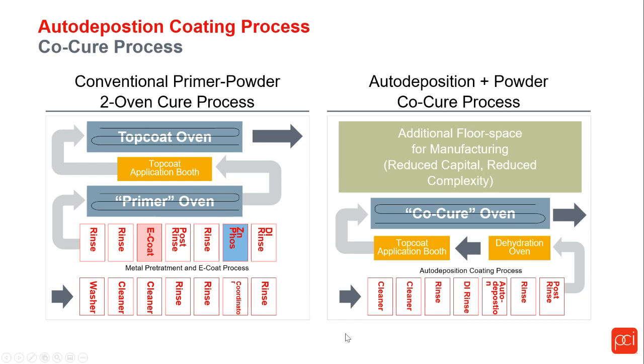With auto deposition, a much smaller line is needed, a much smaller oven is needed from the standpoint of dehydration, and then top coat, and then to the co-cure oven. This saves about 40% floor space versus traditional systems.